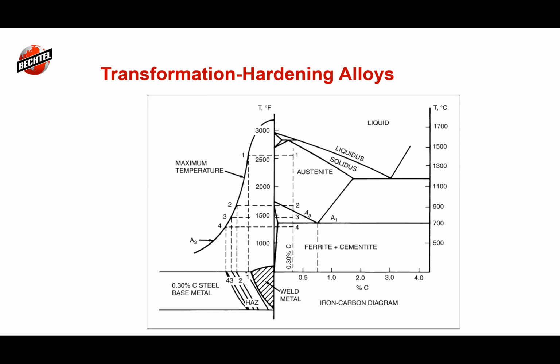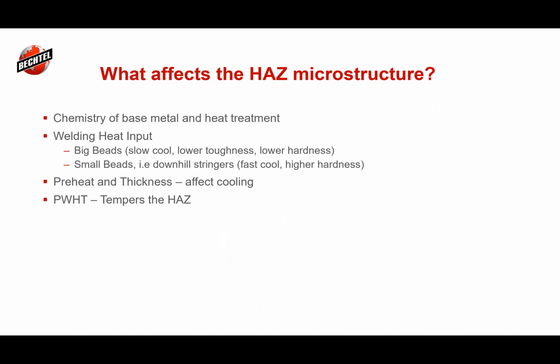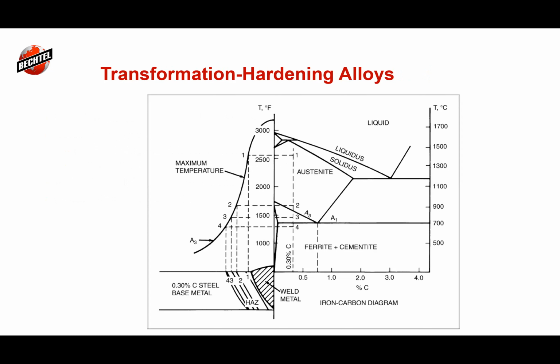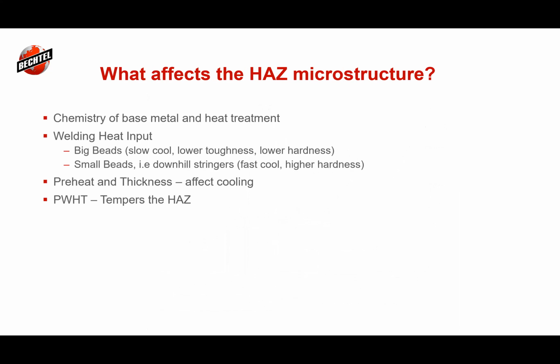Because they know, and we'll see it later, what we all know is that at some point in the heat affected zone, there's a decrease in the mechanical properties. But now when you do it at different stages along that, they're trying to help you find where that decrease is, because there's some sort of softening.